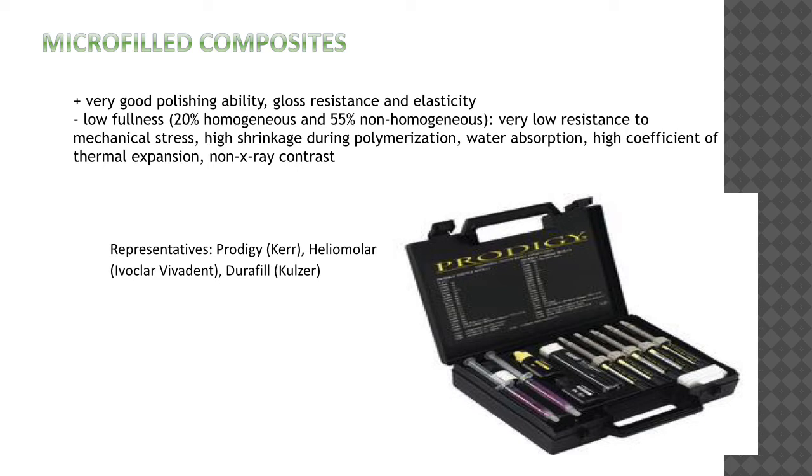Microfilled composites have very good polishability, gloss resistance, and elasticity, but they are low on filler content. The filling is 20% of mass in homogeneous composites and 55% in non-homogeneous composites, very low resistance to mechanical stress, high shrinkage during polymerization, water absorption, and high coefficient of thermal expansion.